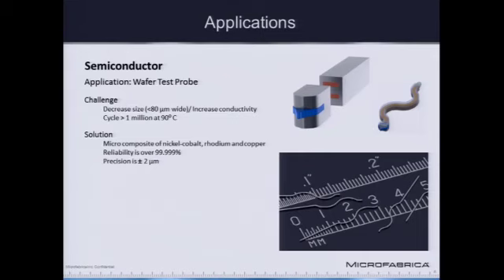We also have embedded copper down the center. This is where we could put high current through it. And then at the tip, we plate this with a rhodium, a pure rhodium material, which is very high wear resistance and makes really good electrical contact. So on this scale, being able to incorporate these 3 materials is pretty unique to our process.